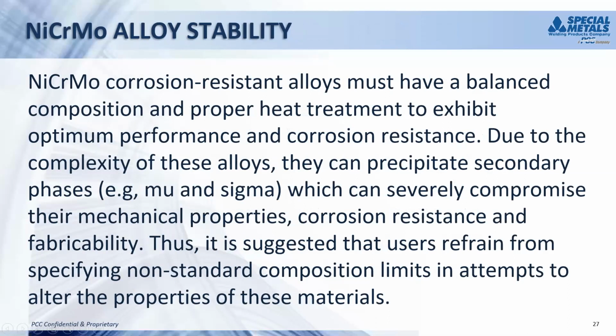Next slide, please. Nickel chrome moly corrosion resistant alloys are fairly complex materials. The elements that make them up can form second phases if they're not properly processed, which can deteriorate the corrosion resistance as well as the mechanical properties and fabricability of the materials. We see mu phase in the nickel chrome moly alloys. Some of you may be acquainted with sigma phase in some of the other alloys and stainless steels. But the presence of these secondary phases is definitely deleterious to the properties of the material.